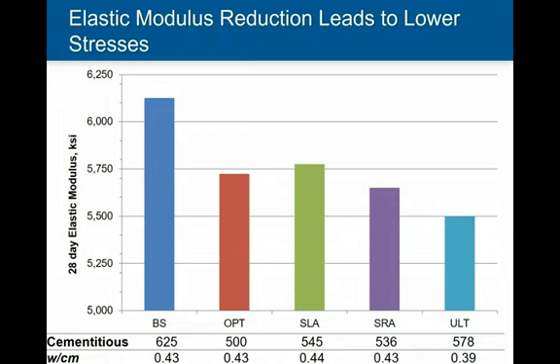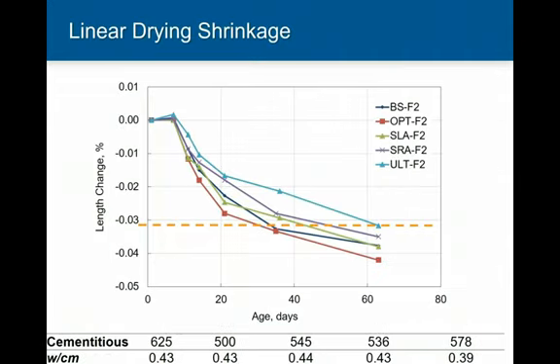And we think that this is in part due to the mitigation techniques, some of these lightweight aggregates and admixtures might be doing some of this, but optimization of aggregates and using the right amount of cement paste can also have this benefit. So we're seeing this relationship that we think is a potential win from a new construction standpoint. And another point to make is we are still tracking drying shrinkage. The linear drying shrinkage, I think, does have a lot of benefit as a performance parameter for long-term drying shrinkage cracking. But I really do believe, as I said previously, that the ring test is the one that we will see the most benefit in.